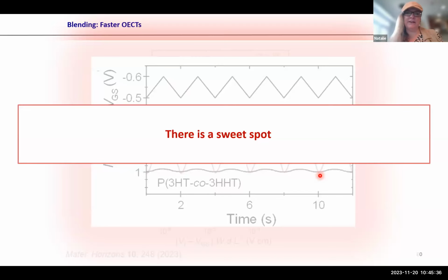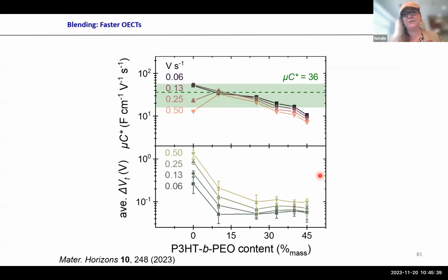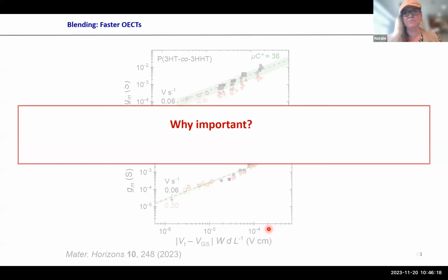I have to see how your time is; I think I'm still fine. There is a sweet spot. Clearly, so far I showed data on 25 weight%. If you now take this mobility capacitance product and the threshold voltage shift, so hysteresis, you see we can actually get a good compromise between mobility capacitance and hardly any hysteresis between the 25 weight%, from 20 to like 30 weight% really. And we still have to understand why it is this specific blend composition.